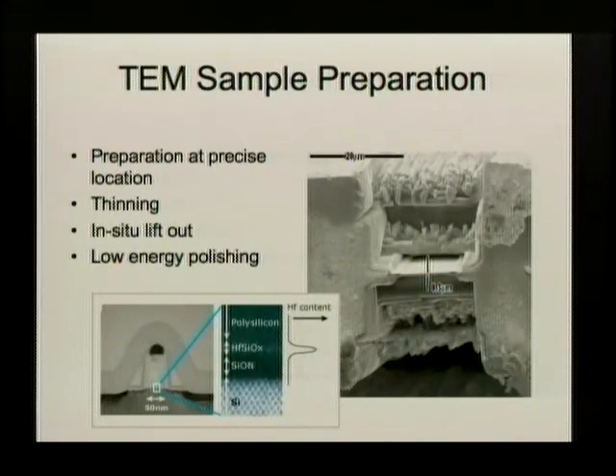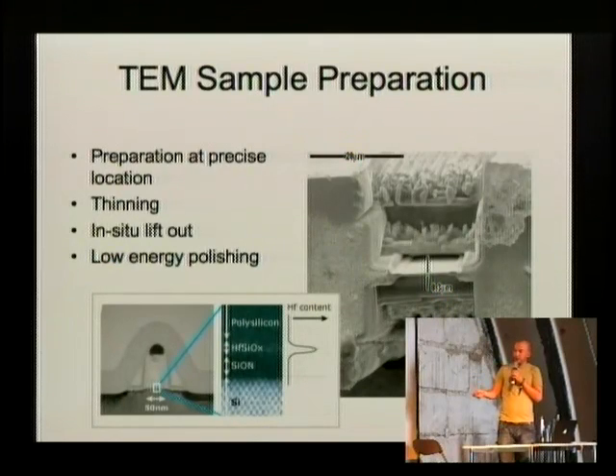So if you're interested in very small structures, you can either reduce the energy of the beam, which unfortunately reduces the resolution, or you can just cut very thin slices. And the focused ion beam does allow you exactly that. For example, if you have a substrate where you know there's a transistor in the middle, and you have pinpointed that this is the transistor that probably failed, you would like to see why it failed, what happened. You can use this focused ion beam to cut out a small lamella. Then you would take this lamella with some manipulator, lift it out, put it either in the same device or in a different transmission electron microscope, and then you can really see a slice through the transistor, and if necessary, go down to atomic resolution.